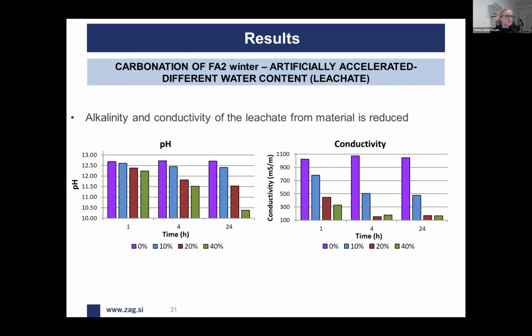The next step was searching for the results of pH and conductivity of those different carbonated ashes, the ash carbonated by mixing it with a different quantity of water. And it's quite obvious that pH lowered with the content of added water. Again, for 40% addition of water, the pH showed the smallest values. A somewhat similar, parallel trend was shown in the case of measuring the conductivity.